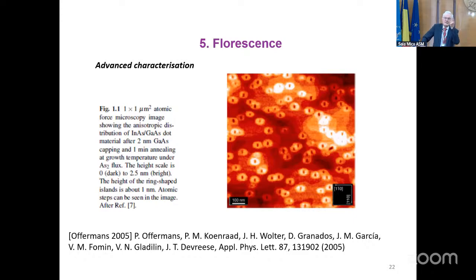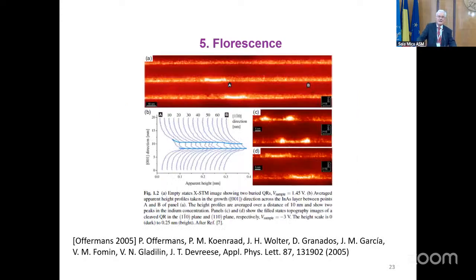Okay. But what is in the center? Do you see black centers? What does it mean? What is in the center? That was the question. In order to answer that question, a very refined cross-sectional STM technology was used. You see here a few micrographs which show results of STM, but not from the top of a wafer. We take a sample with rings and we break it, and then we do classical STM in another direction, from another side, which is usually not accessible.